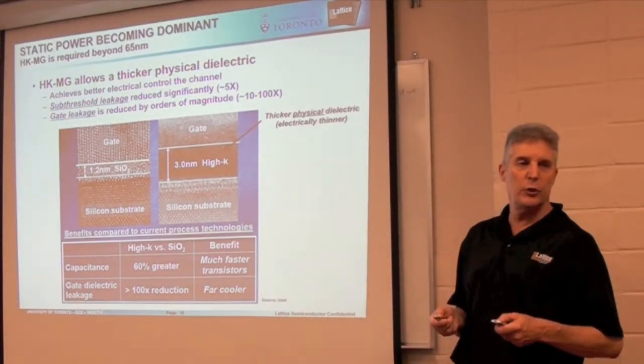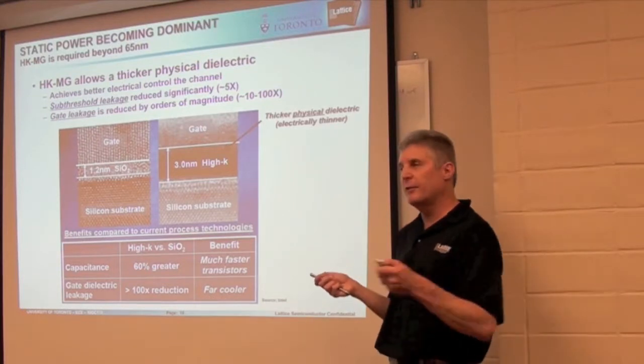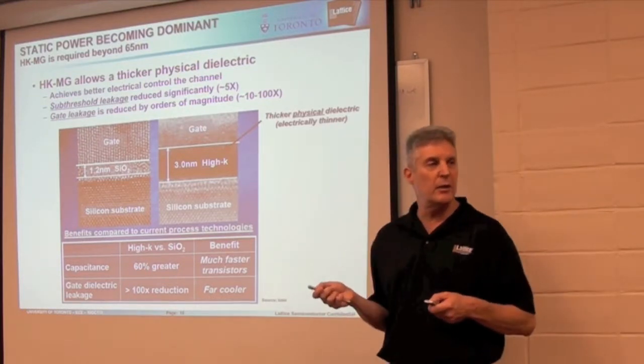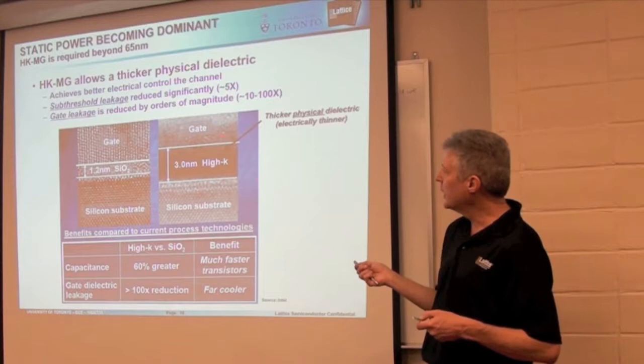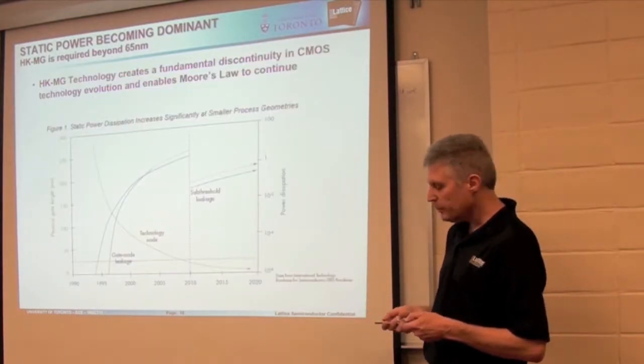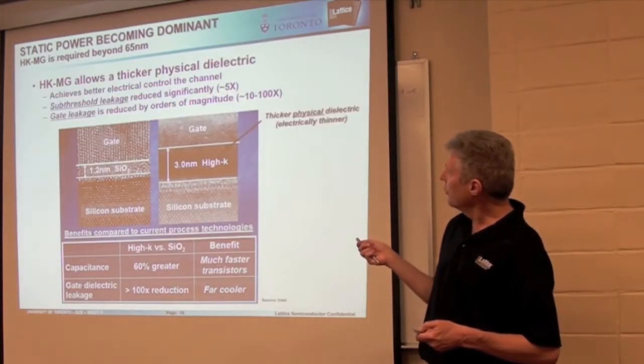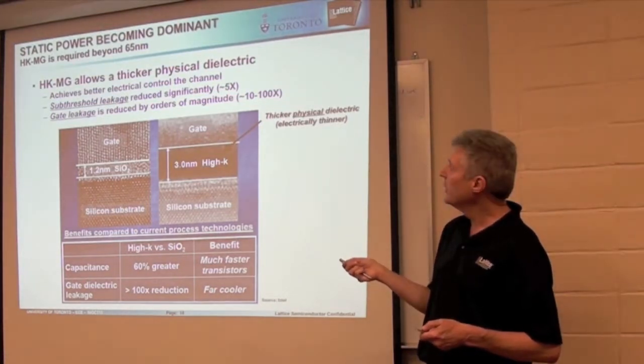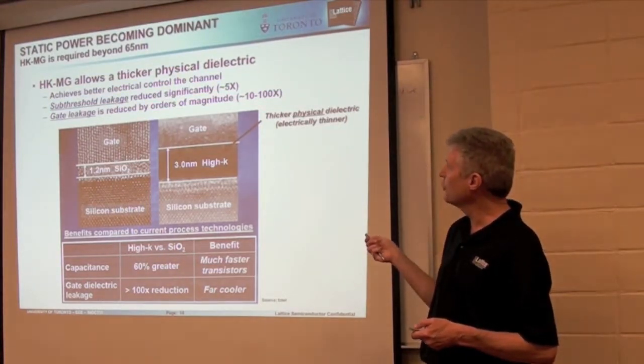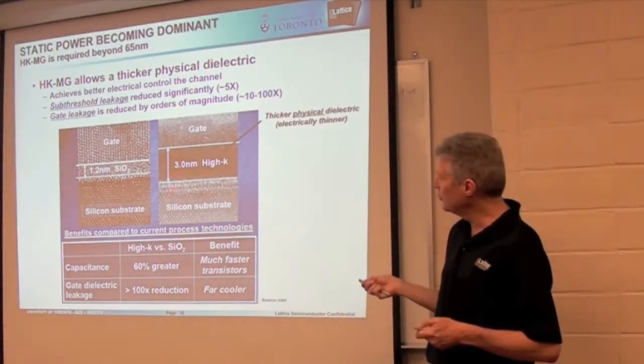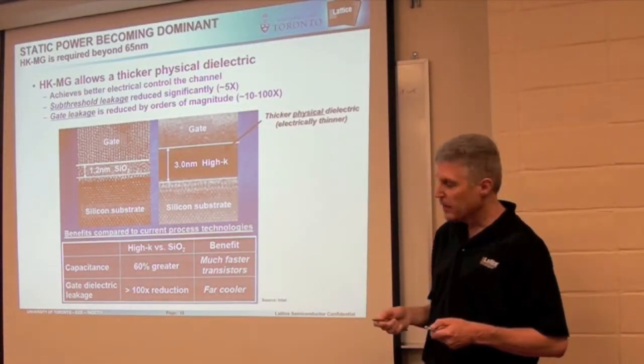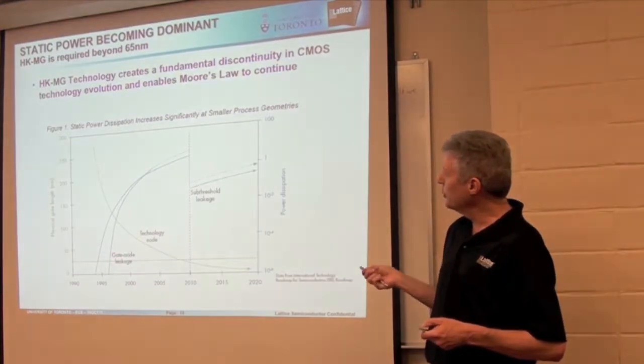So this is, when you hear the term HighK metal gate, every technology beyond 65 nanometers is using it, and this is what it's all about. Now, in terms of orders of magnitude, subthreshold leakage is reduced by about a factor of 5. Gate leakage is reduced by orders of magnitude, 10 to 100x, because you are significantly thicker here. So, what does that do for you in terms of this chart?